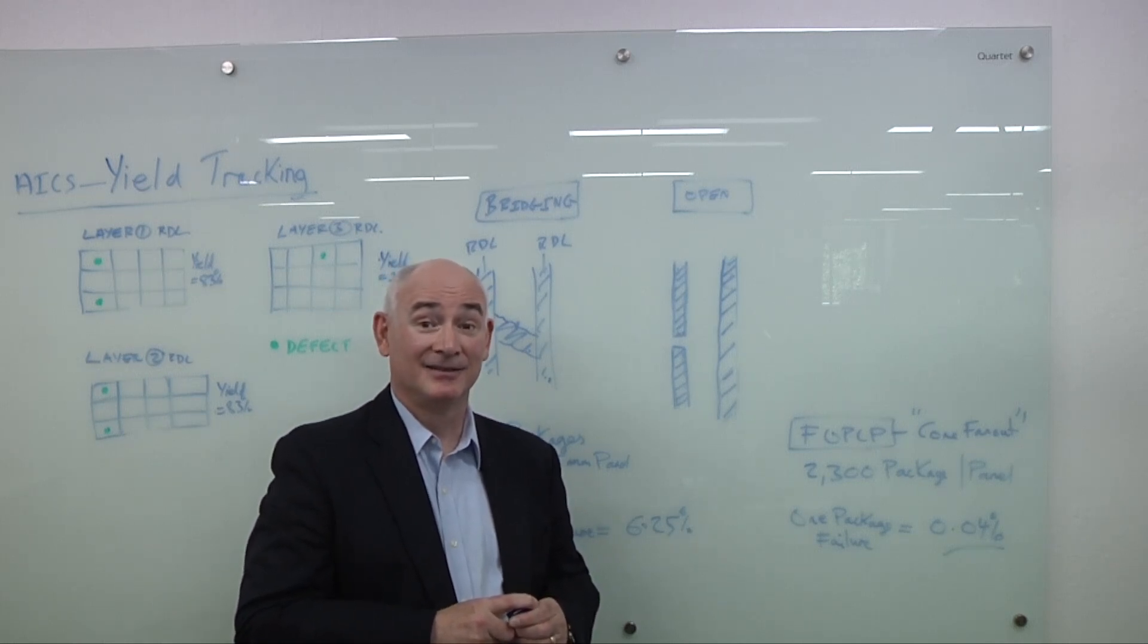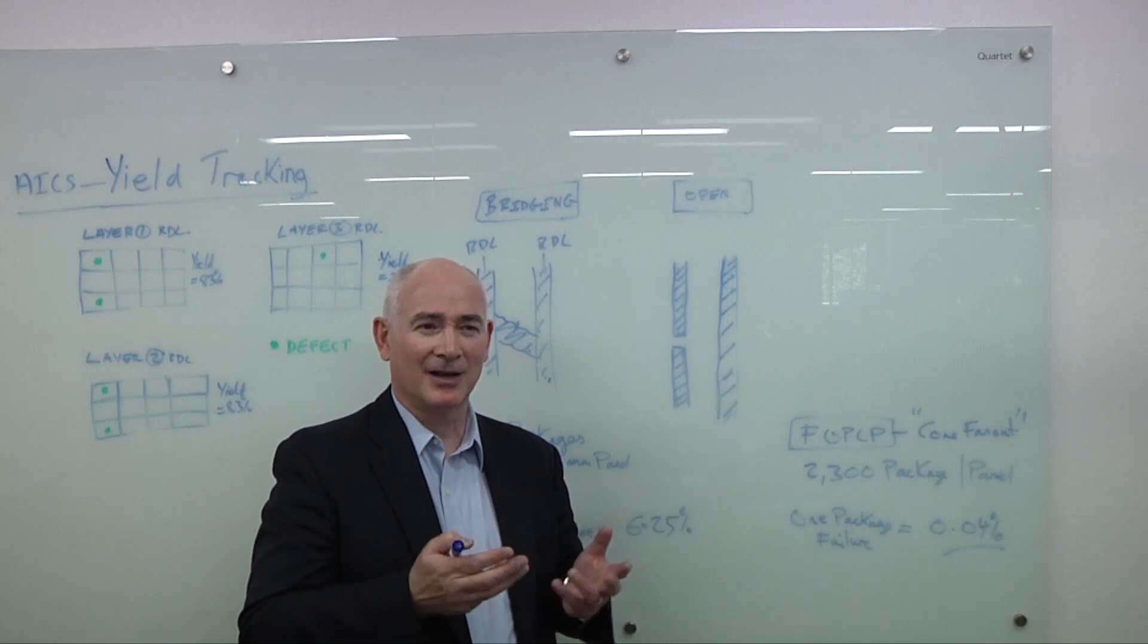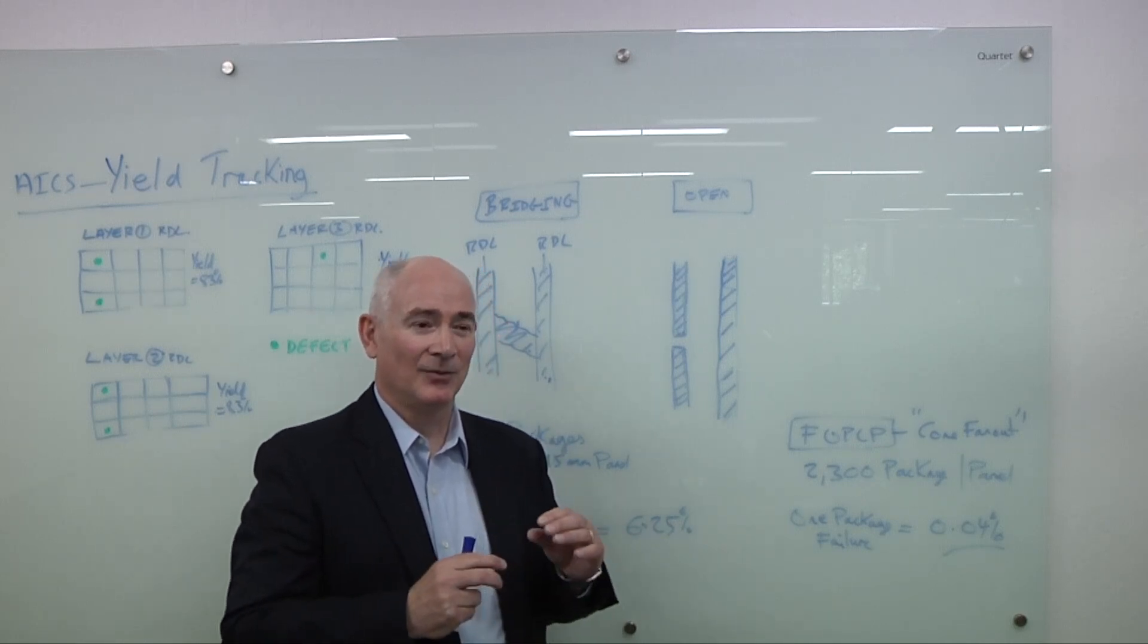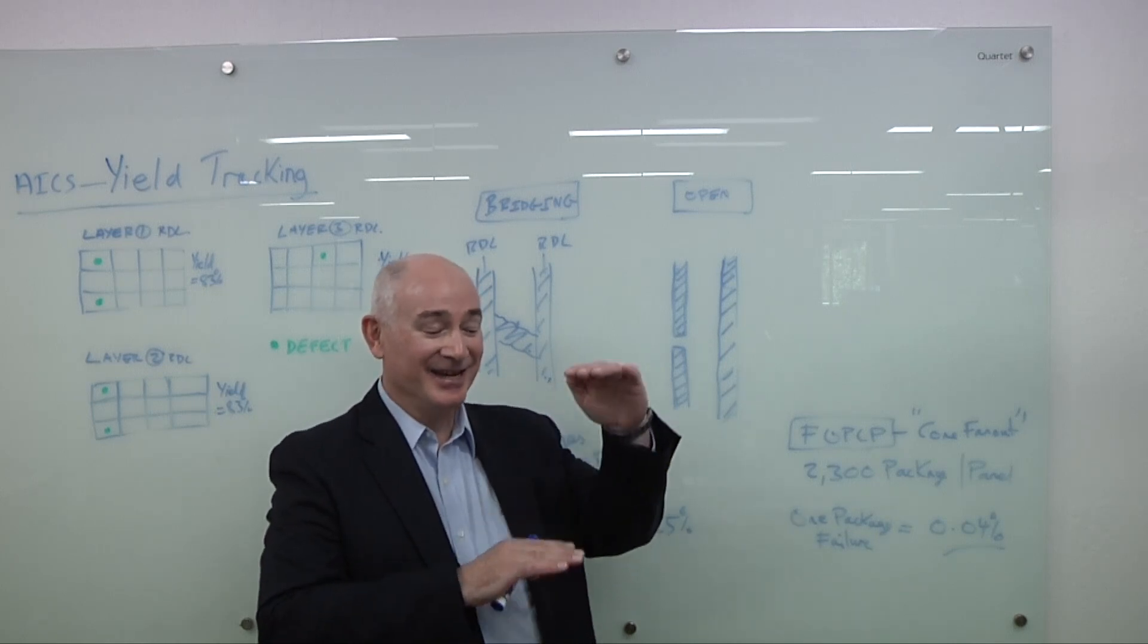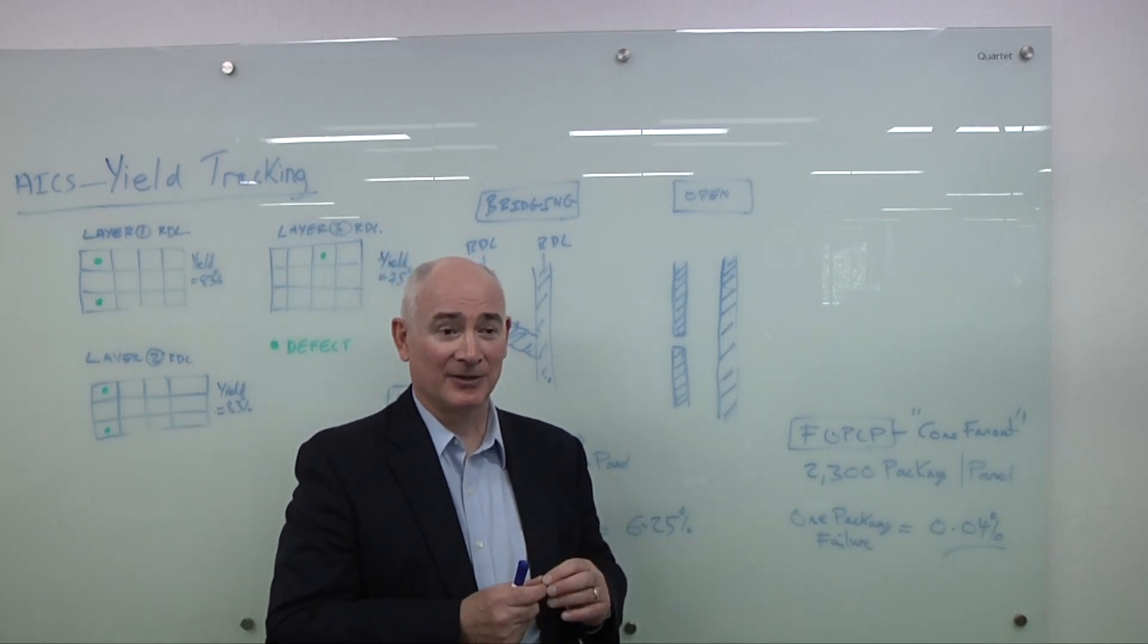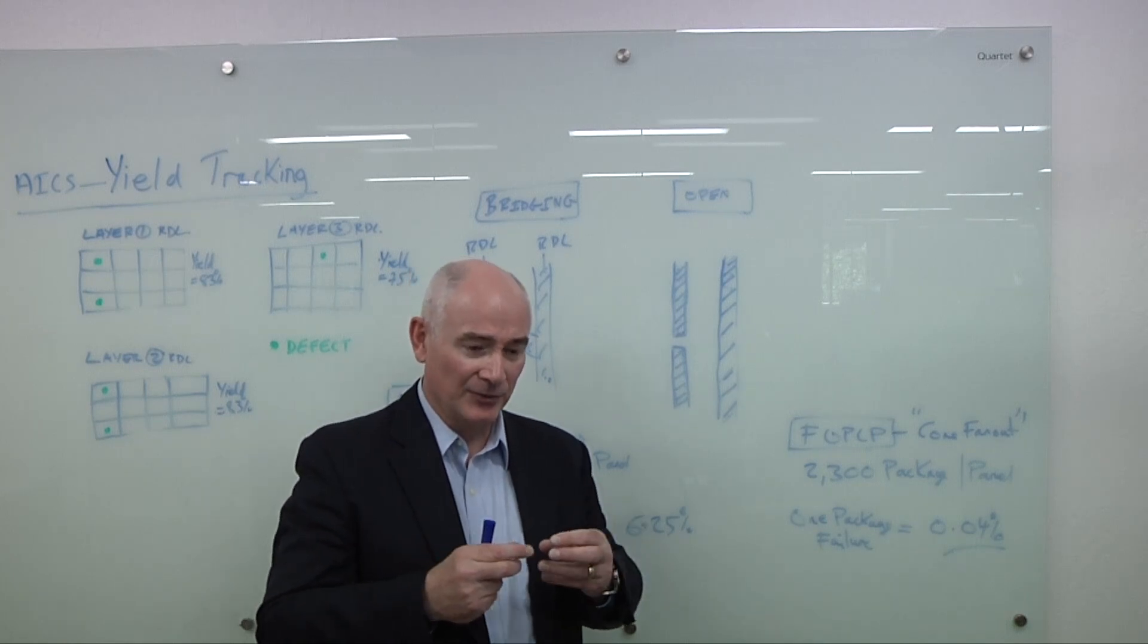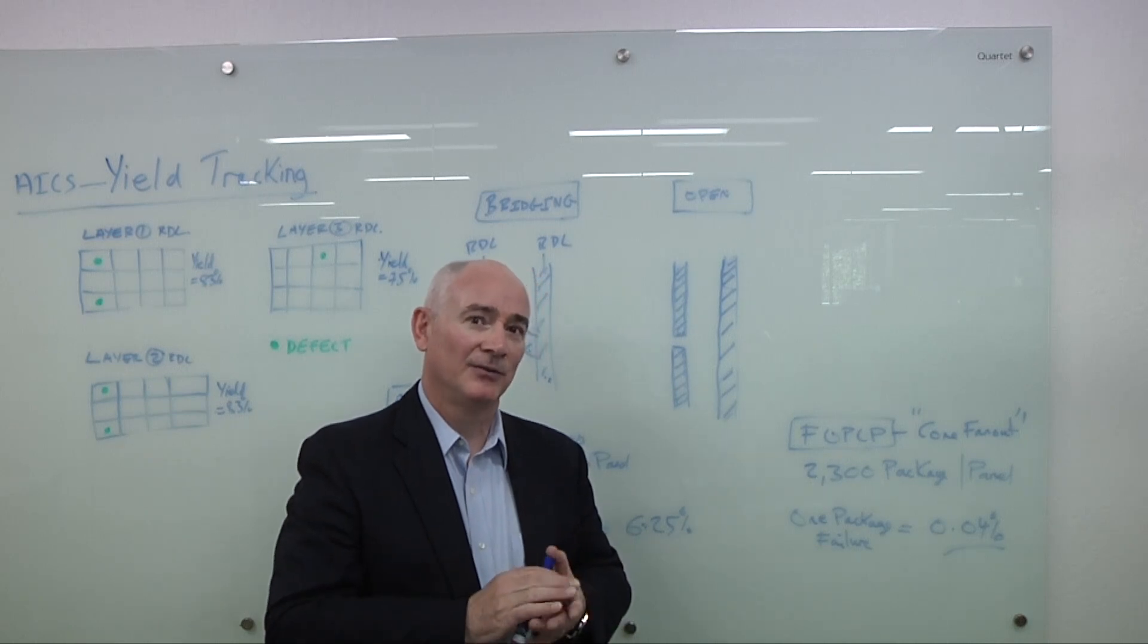But they're also used to dealing with pretty large sheets of glass and fairly thin glass, because if you hold it up, you'll probably break it. This is much thinner though, right? That's right. Now we're talking about 300 micron thick glass. People are pushing down to sub-100 microns. That is really delicate glass. But I think when you talk about the number of layers you're going to put on top of it, you have to remember now you're doing a Z change as well as an X-Y change. So we've seen substrates go from say 200 microns up to 3 millimeters in thickness, because there's just so many layers. But with glass, if you can start thin enough and you have higher resolution performance, you'll need less layers. So as a result, the whole stack might be slightly thinner and give you an advantage there.